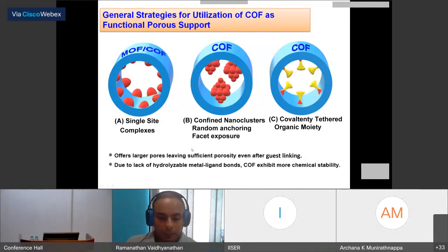And one important aspect compared to MOF is that COF typically, as I showed you in the previous slide, can have pore sizes in the range of 10 angstrom to 70 angstrom, which means even after anchoring such species or decorating the COF with such species, you will still have enough porosity left, which is very critical for the access of these sites, which are active sites.